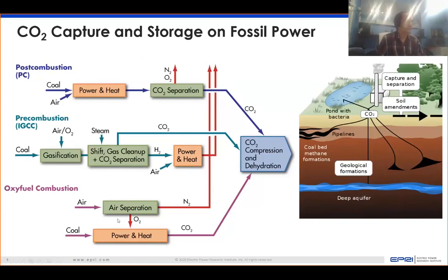And then oxy-fuel combustion is where you separate air, essentially oxygen, nitrogen, and you combust a fuel in a pure oxygen or mostly oxygen stream. And in all these approaches, there's a separation step involved, and that really is the driver for the cost and energy involved in CO2 capture and storage. But once you have the CO2 separated, you can compress it and dehydrate it, and typically you're going to inject it into aquifers of some kind, which are subsurface, which is the capacity I mentioned in the previous slide.